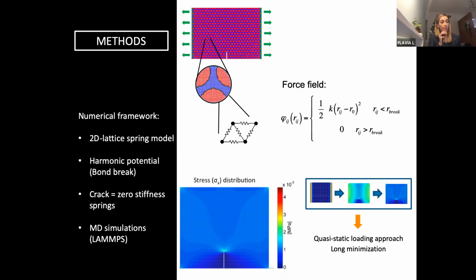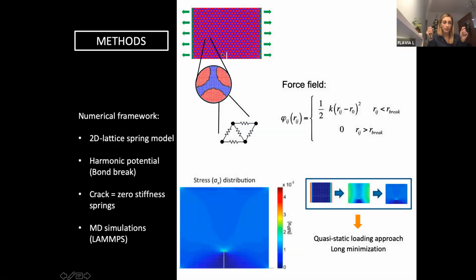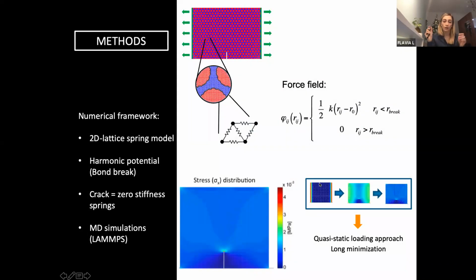All the simulations are run using LAMMPS, a molecular dynamics simulation code, and we use a quasi-static loading approach, which means that we systematically apply strain at the ends, followed by energy minimization, which allows us to have a good homogeneous redistribution of stresses without having stress concentration at the clamps, at the lateral edges.